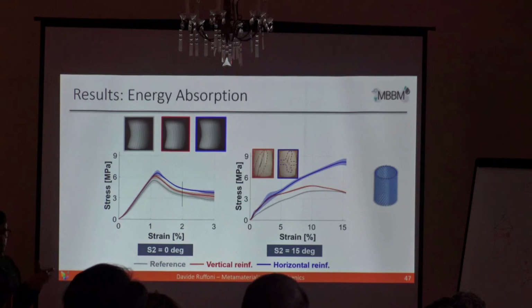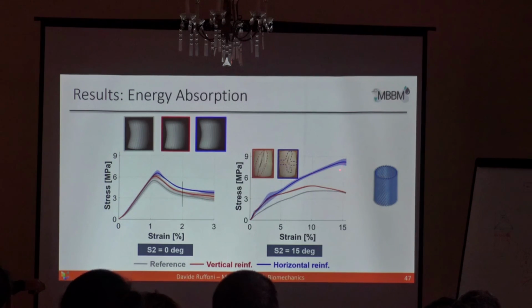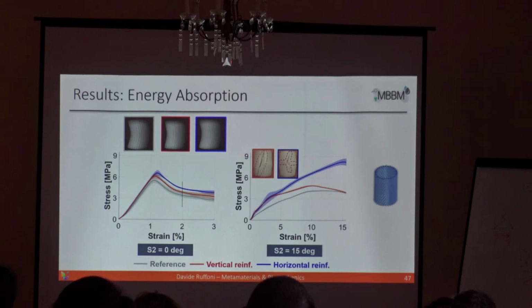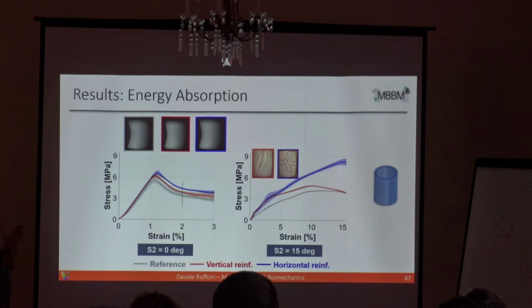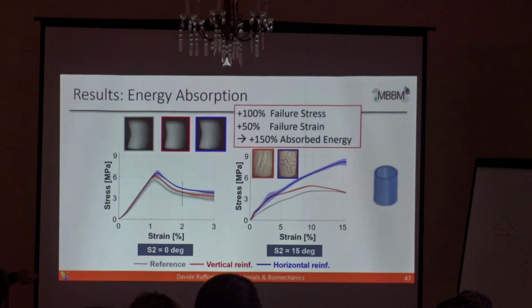But when you introduce horizontal reinforcement, then you are really able to significantly increase the peak stresses and, if you want, the energy which is absorbed in this failure process. This is a typical fracture that we observe in the system without horizontal reinforcement: fracture in the matrix between the fibers. And here are fractures that we see when we add circular reinforcement, and you see that the fracture is also moving from, let's say, a tilted direction to a more horizontal direction. So the way it breaks dissipates a lot of energy, and so we have a 150% increase in the absorbed energy before failure.